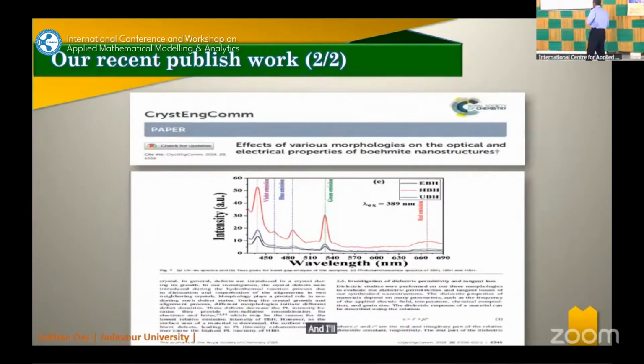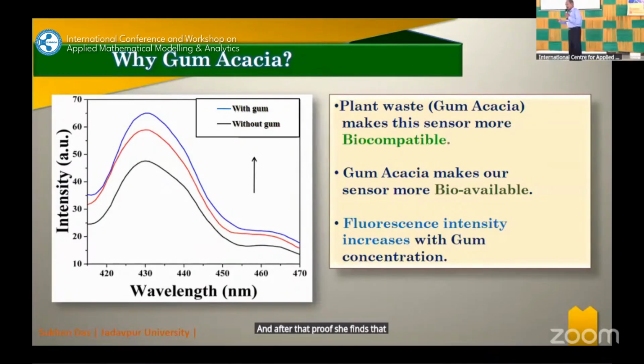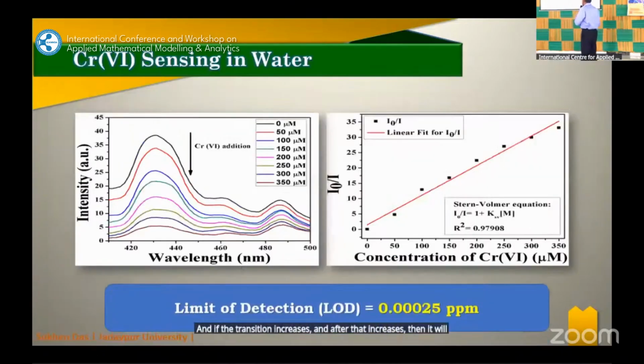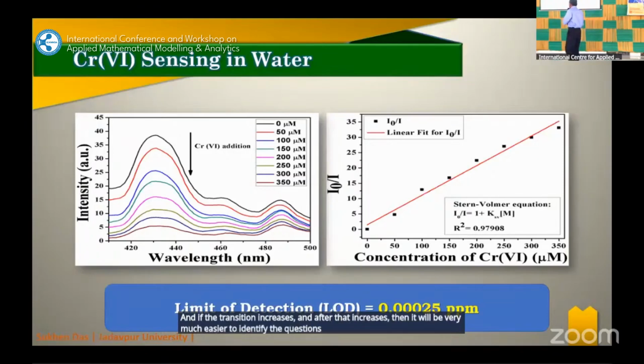And after that, we find that if we use a UV spectrophotometer, then there is an absorption peak near about 430. If we increase the percentage of Gum Acacia in the Boehmite, actually Boehmite has the absorption at 430 nanometer. And if it is the doping of the Boehmite with the Gum Acacia, then the absorption increases, and then it will be much easier to identify the fluorescence property of the Boehmite.